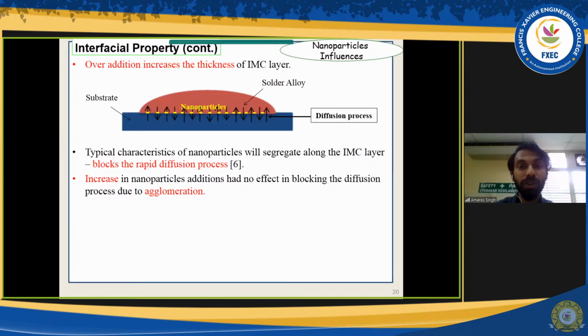So you can see I've separated the solder alloy and the substrate. Diffusion process is highly active at the interface between the maroon or red colored solder and the blue colored substrate. So nanoparticles being an active element, of course, they will try to slot in at the highest energy area, and the highest energy area is where the intermetallic layer is formed. So when these nanoparticles are there, they will block the diffusion process. That means, let's say there is a thing from the solder that tries to merge with the copper in the substrate. Yes, it can, but nanoparticles will actually reduce the diffusion process. Basically, it will not produce a high rate of diffusion and therefore preserves a thin IMC layer, intermetallic compound layer.